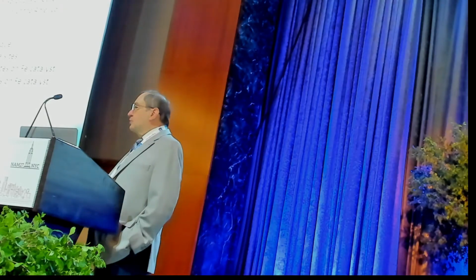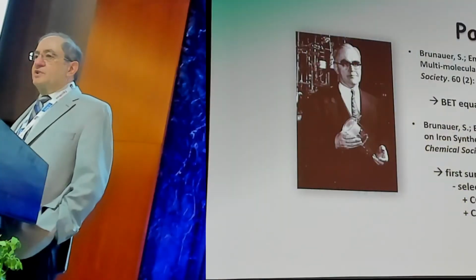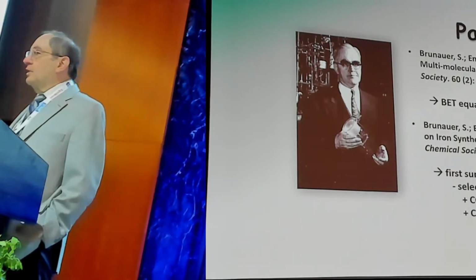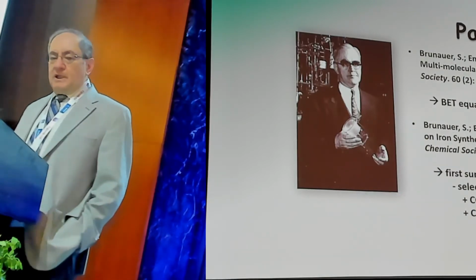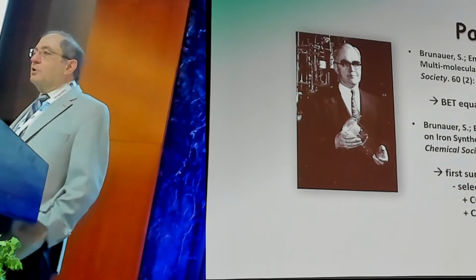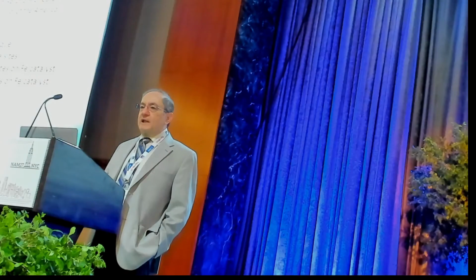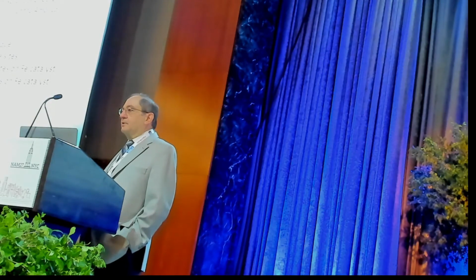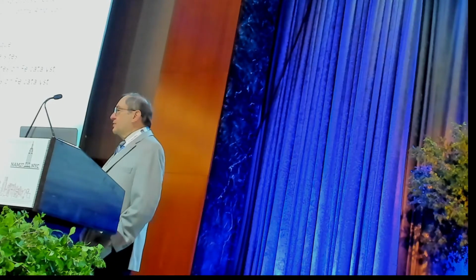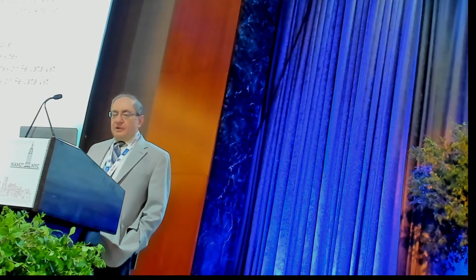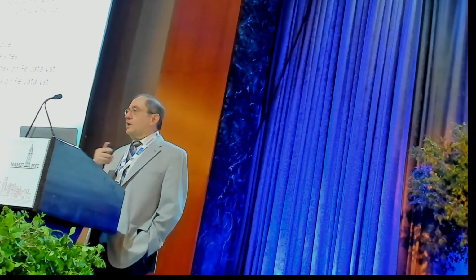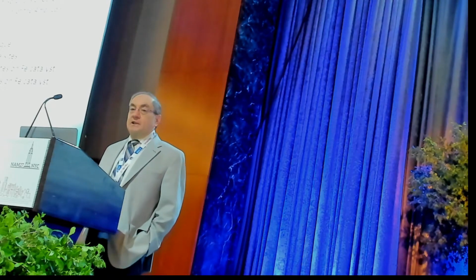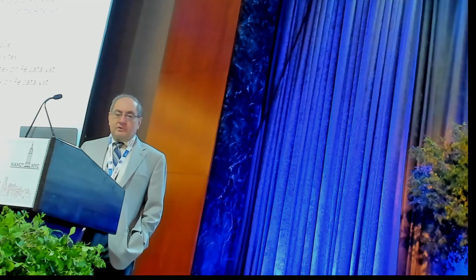They used selective chemisorption. They were trying to understand ammonia synthesis catalysts, which is iron, promoter, alkali, potassium, sodium, calcium, and they developed CO2 chemisorption to count the number of basic sites, potassium, sodium, calcium. And they used CO to titrate how many metal sites were exposed. It's the real first surface characterization that I'm aware of. And it's really groundbreaking. I just want to emphasize these phenomenal accomplishments that we rely on daily in our catalysis world and research.